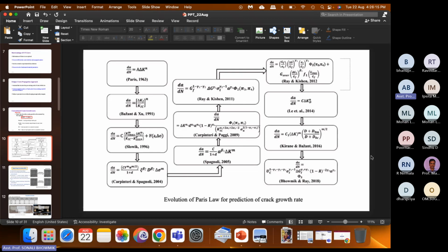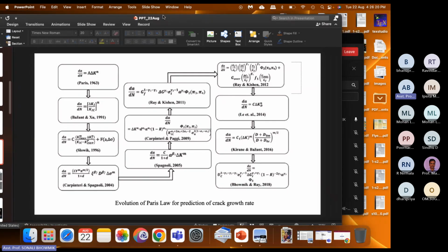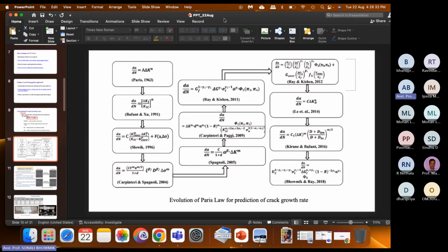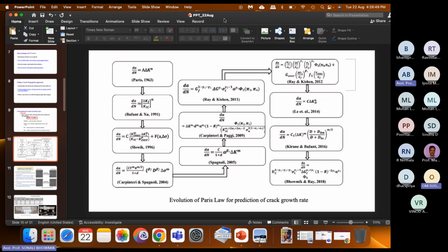If you can see, the last expression is dealing with many more parameters like critical energy release rate, crack length, and other parameters like stress ratio, energy release rate, sigma t meaning tensile strength, and many more things. So these are some developments in this area, where the attempt was to develop a fatigue crack propagation model which can accurately predict the fatigue crack growth rate, and finally the fatigue life of a structure.